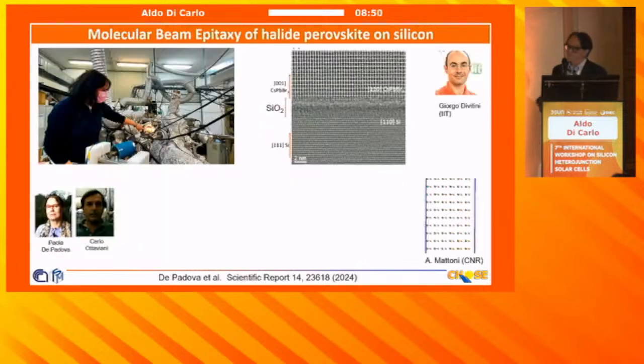Before going to the next tandem solution, I want to show you something that could be the next step to put perovskite on silicon. We spent 4 years setting up a molecular beam epitaxy of perovskite, and this is one of the first examples: a large band gap perovskite on top of silicon, an epitaxial growth of perovskite on silicon. There is a buffer layer of silicon dioxide. Without this buffer layer, it doesn't work epitaxially.